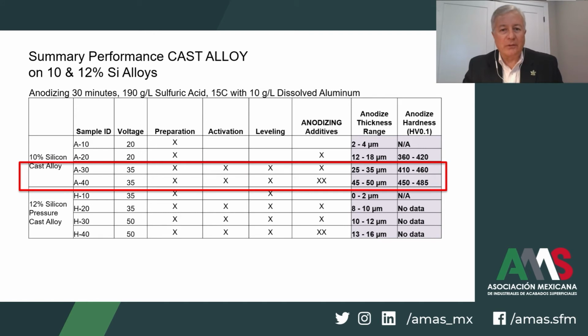Furthermore, in the next series, incorporating some of the stage 1 acid activation step with leveling to improve the surface finish further doubled the oxide coating formation from 12 to 18 microns up to 25 to 30 microns, and further increased the oxide up to 45 microns with increasing the additive concentration to the anodized solution. So for the 10% silicon intermetallic cast alloy, using both stage 1 and stage 2 processing with the proper selection of stage 1 activation and the leveling chemistry demonstrates the advantages of incorporating both stages into the processing of the high silicon cast alloy. This also maximizes the oxide hardness, which is shown to be more resistant to abrasion.